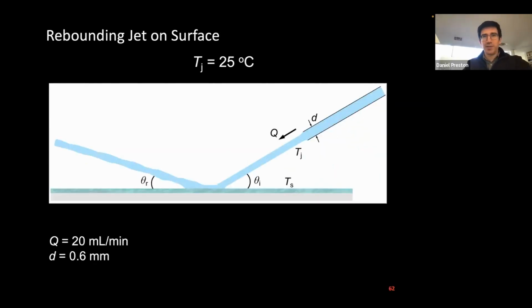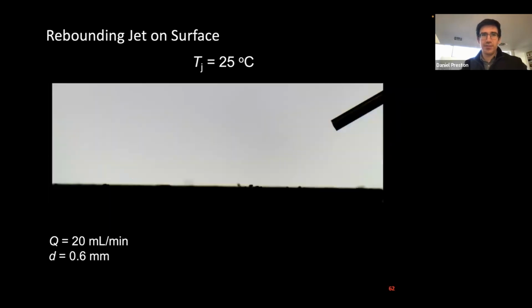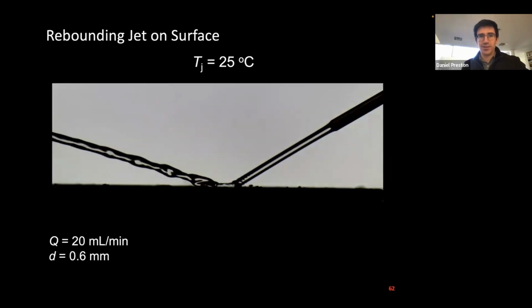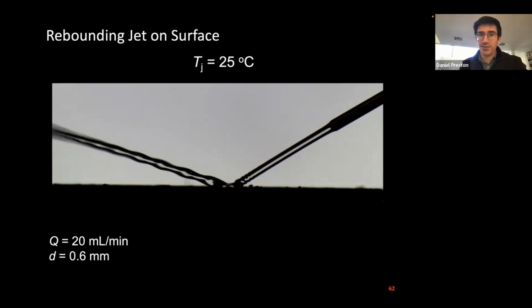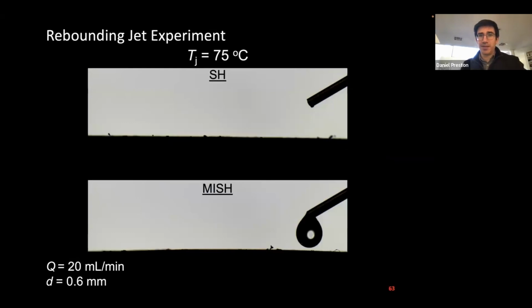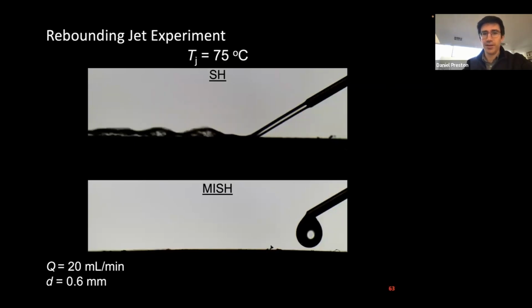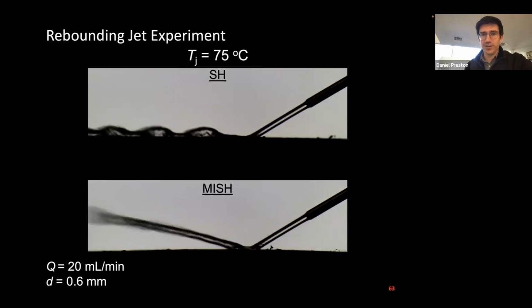So we did a few other experiments, and we get into some more qualitative stuff here. We did some rebounding of a jet on the surface. This is at 25 degrees Celsius, so room temperature, and it looks maybe as you'd expect, it bounces off. Then we went up to 75 degrees Celsius water. In this case, we compared the superhydrophobic surface only, the spray-on coating only of the superhydrophobic material, to our mesh coating, and found a pretty marked, distinct difference in performance. So we were encouraged by that.